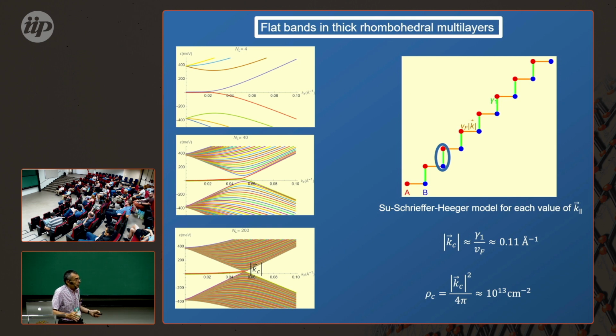So it has a topological phase and a non-topological phase. Irrespective of whether you have a kind of inversion of the gap in the middle, you will have localized states at one end of the chain and at the other end. But you're not worrying about solitons here, right? And it's just the zigzag, the bonds being different, which is just a Peierls state, right? However, it's spirals. So I'm only worried about the edge states you get at the top. But it's true that if you create a stacking defect, that may play the role of a soliton, and then in addition to a two-dimensional electron gas at the bottom and at the top, you may have somewhere in the middle another two-dimensional electron gas.